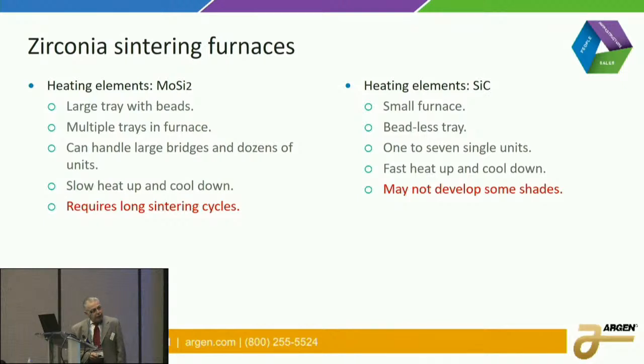Okay? With the moly disilicide, generally you want to have a large furnace. You want multiple trays. It can handle large bridges, and this requires a slow heat up and a slow cool down. So with the moly disilicide, for most of these large furnaces, you have to rely and stay with the long sintering cycle. So you can't take a furnace and modify it to do a fast speed. You can't take the moly disilicide furnace as a regular furnace and just go faster with it. You can put any number you want on the program, but the furnace is not necessarily going to react that way.